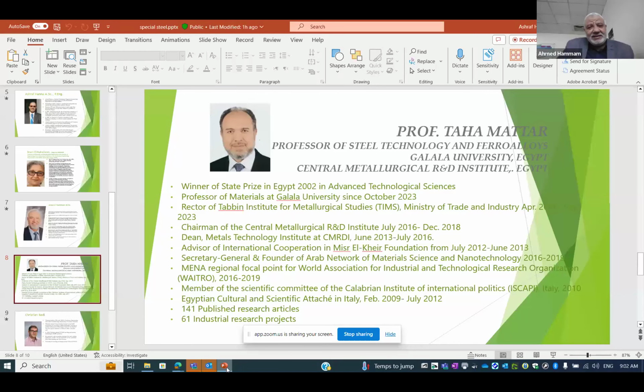Thank you very much. A very quick question also from Derek van der Schoorn. He asked if you can make killed steel reach this 15 ppm only by adding some aluminum or silicon, without a vacuum degasser, or do you still need a vacuum degasser? No, you still need vacuum degassing to ensure that the total heat has this level, because by adding some alloy, aluminum or others, you cannot ensure that the whole heat from start to end has the same constant level of gases. But by using vacuum degassing, you are ensured that the heat stays 20 minutes under vacuum conditions, extracting all the excess gases.